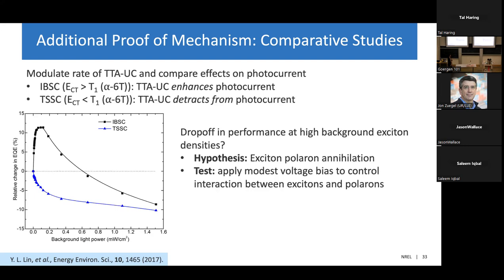And for the intermediate band solar cell, where we expect that to enhance the photocurrent, as we increase the background light power, we see a rise in the photocurrent production and eventually a drop off. However, for the triplet sensitized solar cell, the increased triplet-triplet annihilation produces a decrease in the photocurrent as we expect. So this, at least initially, is in line with our expectations.